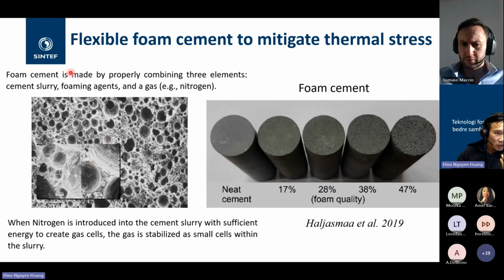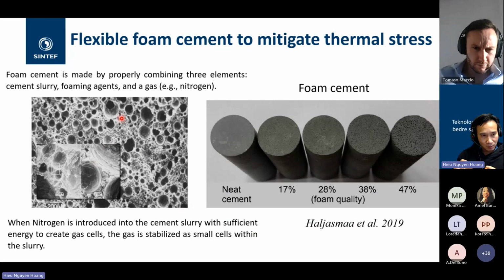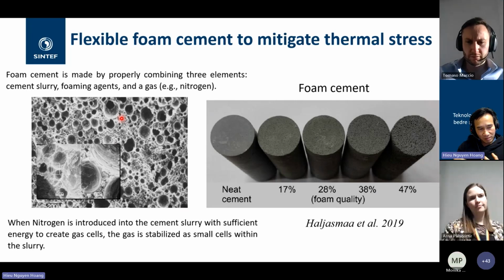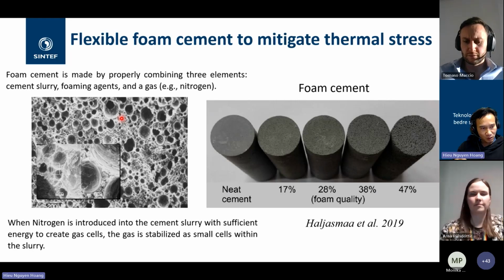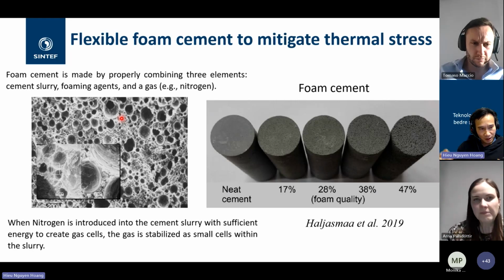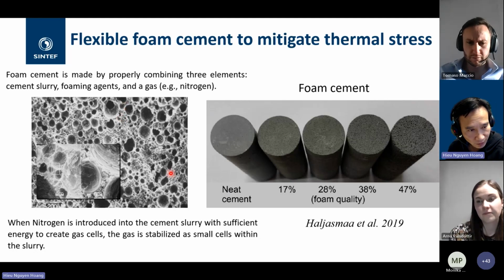And the foam cement, as you see, is made up by properly combining three elements: cement slurry, foaming agents, and gas such as nitrogen. When we inject the nitrogen gas into the cement slurry with sufficient energy, like inner pressure, we create gas cells, and the gas is stabilized in small cells within the slurry, creating a lot of bubbles and porosities, increasing the flexibility of the foam cement system as a whole.